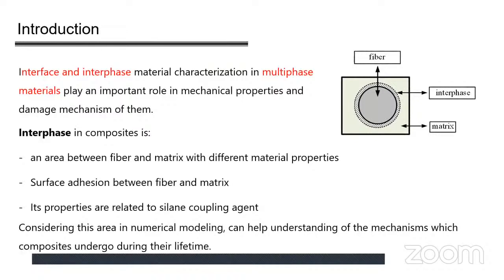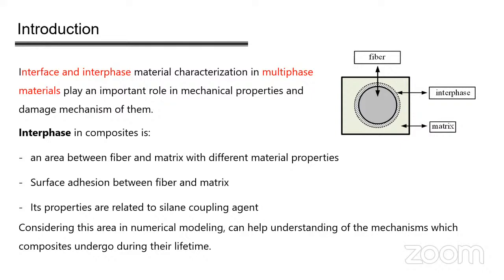Interface and interphase material characterization in multi-phase materials in general play an important role in mechanical properties and damage mechanisms. Especially in composites, the interface is an area between fiber and matrix with different material properties, as shown typically in the figure. On the other hand, it is called surface adhesion between fiber and matrix. These properties are related to the silane coupling agent, and considering this area in numerical modeling can help understanding of the mechanisms which the composite undergoes.